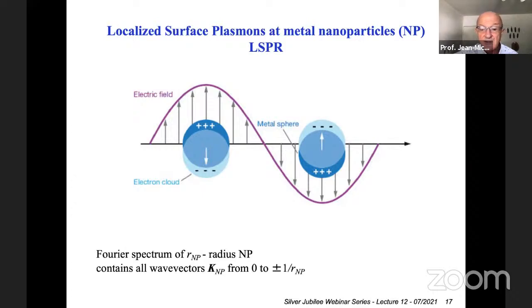So in that case, we send light onto a metallic nanoparticle. The electrons in the metallic nanoparticle are directly excited by the light. There is a coupling, and that polariton is called the localized surface plasmon at the metal nanoparticle. This can be resolved by solving the interaction equation, the Maxwell equation, at a metal nanoparticle, which is solved by the Mie scattering theory in that case.